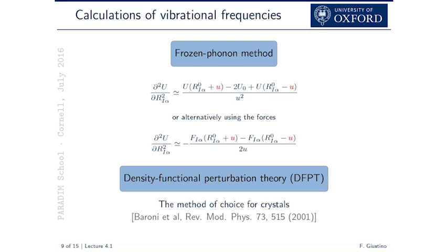So people prefer to look at the force after you displace an atom, and then you do the calculation with the atom displaced the other way around. You take the difference, and that's basically an approximation for this second derivative. Okay? So all of this is equivalent theoretically. This is way faster because you have to do fewer calculations. So that is essentially a way of using finite difference formulas for calculating second derivatives of the total energy.